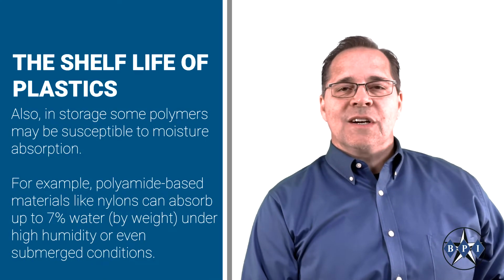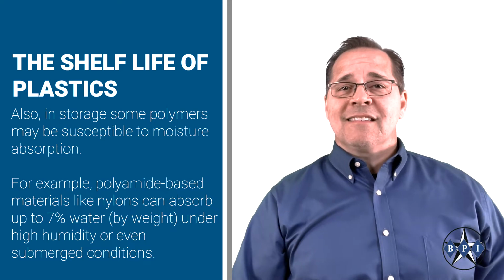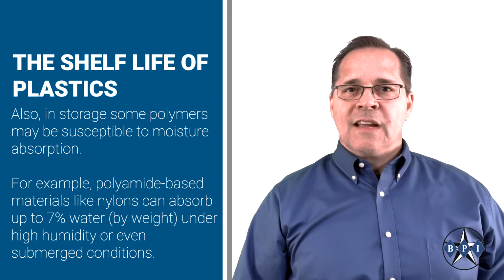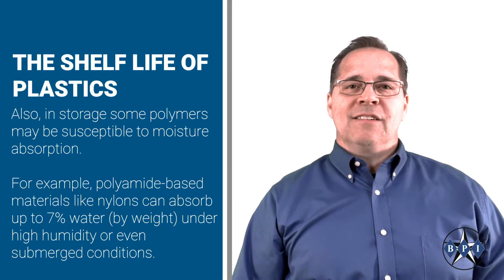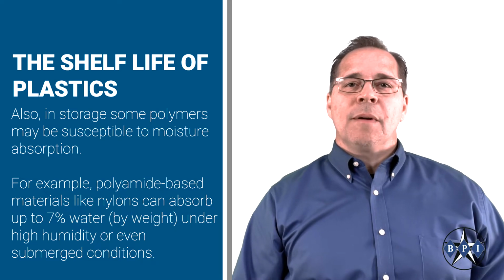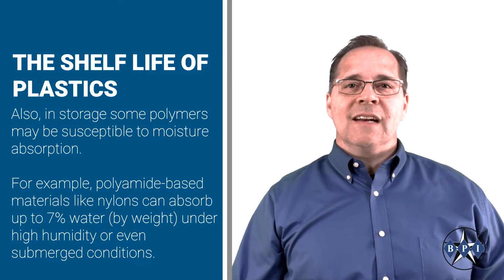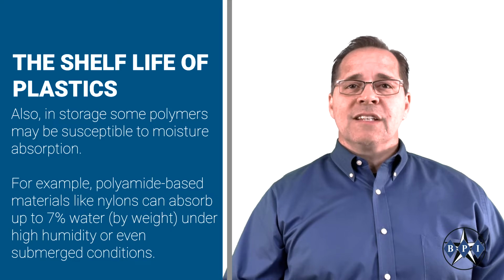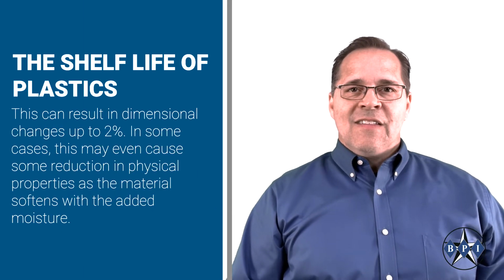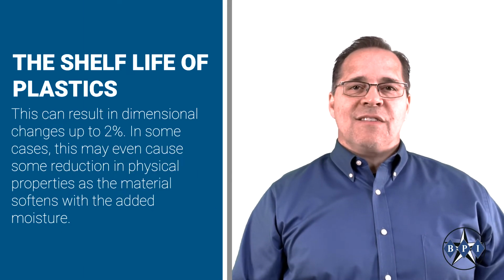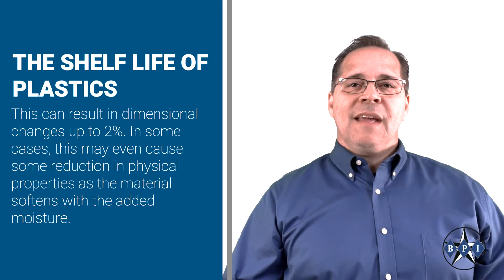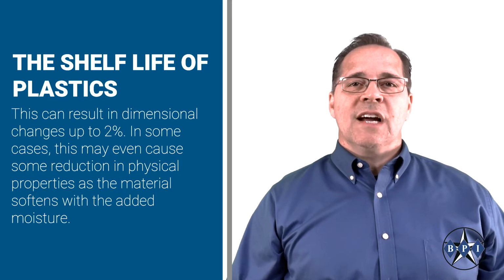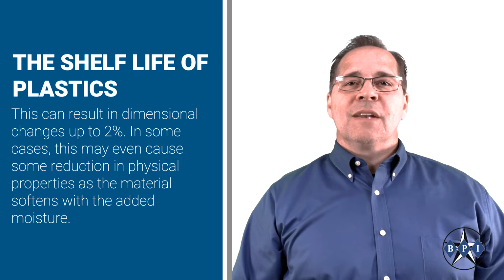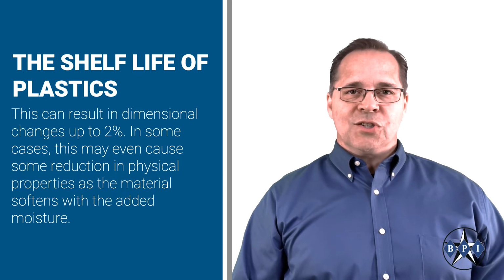Also, in storage, some polymers may be susceptible to moisture absorption. For example, polyamide-based materials like nylons can absorb up to 7% water by weight under high humidity or even submerged conditions. This can result in dimensional changes of up to 2%. In some cases, this may even cause some reduction in physical properties as the material softens with the added moisture.